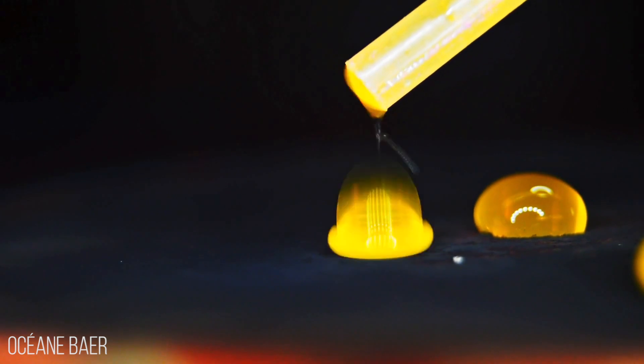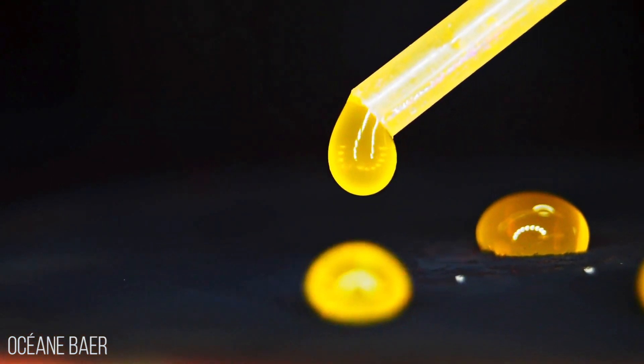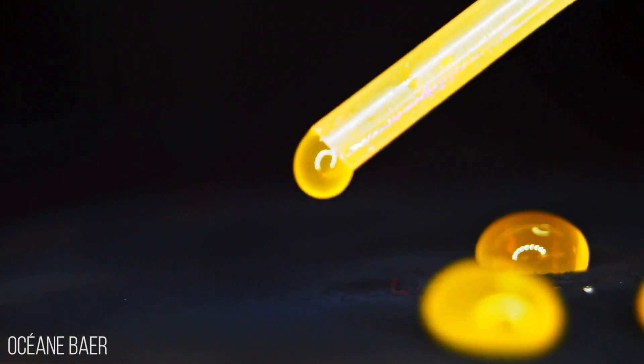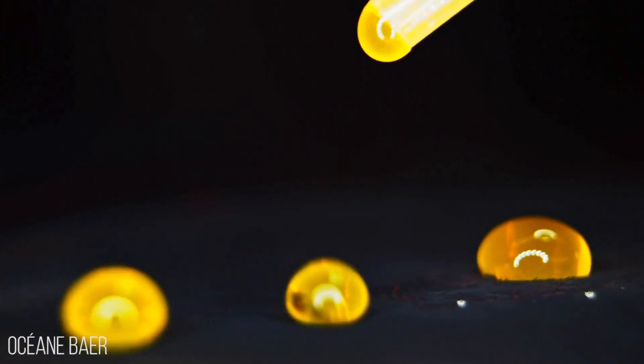The first step is creating the super hydrophobic surfaces. To do that we take a silicon wafer, we go to a clean room, apply the nanotexture, and then add a hydrophobic coating, and that's what creates a super hydrophobic surface — so incredibly water repellent and textured on the nanoscale, which is important because crystals don't form in this nanotexture.